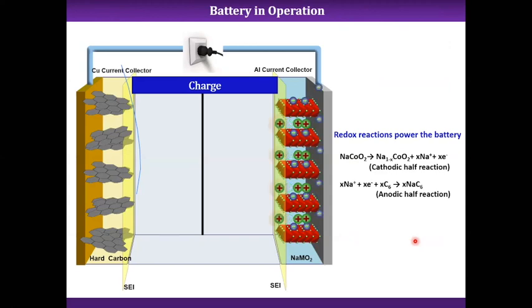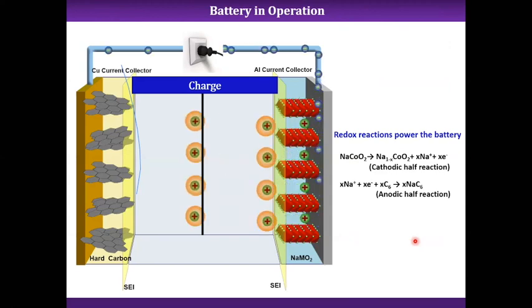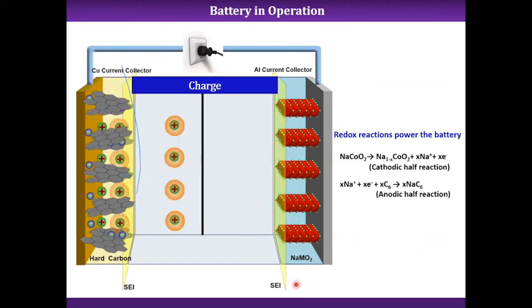Battery in operation is like this. When we are charging it, let's say I have a sodium transition metal oxide system. When I charge it, the sodium, or if I take a lithium system, correspondingly lithium, during charge goes from the cathode side to the anode side. These are layered materials, so they conveniently store here during charging. And these are the reactions which happen here. Let's say my cathode is sodium cobalt oxide. So I give some sodium, let's say x sodium out. So it becomes Na1-xCoO2 plus x Na+, which comes out here, and some electrons. Electrons go in the outer circuit, and ions go through the electrolyte.